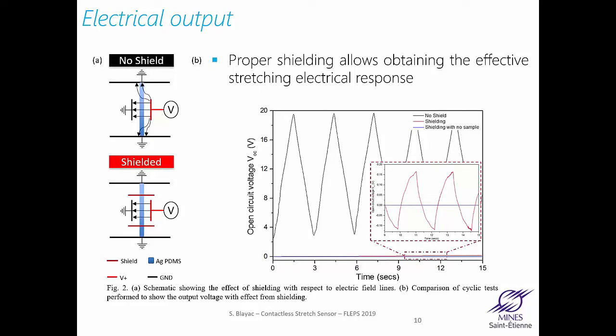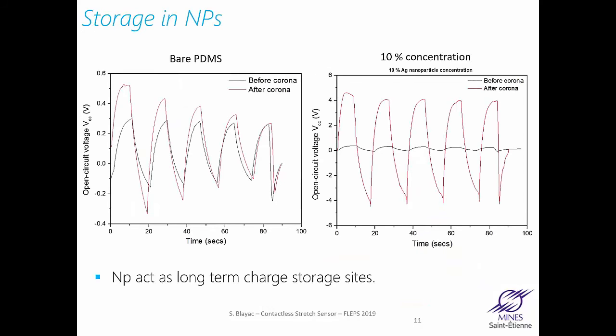very strong and really straight. And this is not the actual response of the electret, but this is due to the variation of the position of the fixture here. So you have to shield the system so as to extract the exact response of the variation of the charge. And here you obtain a nice variation that will be an image of the stretching of the material. Then, if you want to evaluate the capacity of storage of our nanoparticles, we make a test just by using, for example, bare PDMS and then PDMS with 10% concentration of particles. And we can see that if we make some corona on the bare PDMS, we are making a charging but losing rapidly the charge, and the signal is rather poor. But if we use then 10% concentration of charge, we have a rather high signal, and we can monitor wirelessly exactly the stretch of the signal.